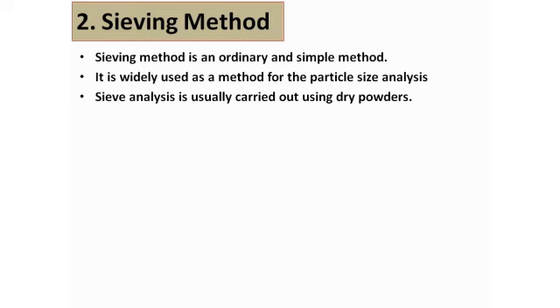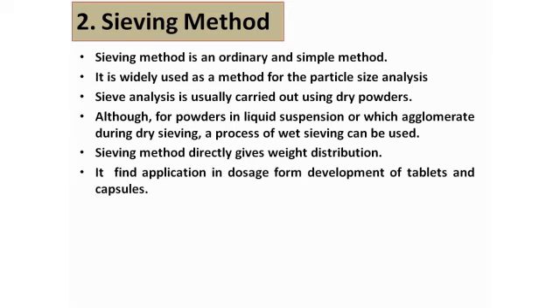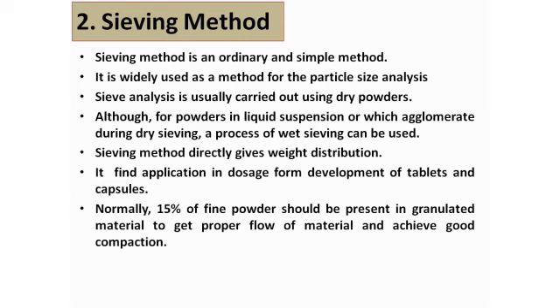The sieve analysis is usually carried out using dry powders. Here it is very hard to use lumps but still we can use it. Although for powder in liquid suspension or which agglomerate during drying, in such cases a process of wet sieving can also be used. Now the sieving method directly gives the weight distribution based on the differentiation of the particles based on their size. It finds application in the dosage development of tablets and capsules. And one thing you should remember: 15% of fine powder should be present in the granulated material to get a proper flow of the material and achieve good compaction.